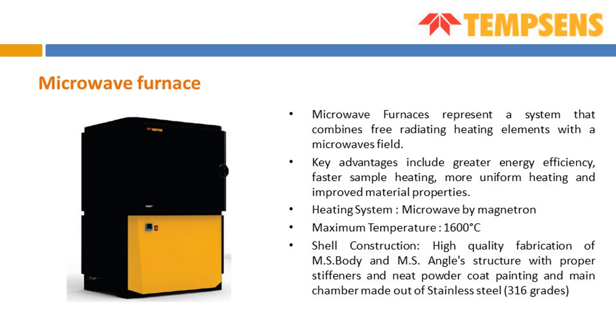Maximum temperature we can go up to is 1600 degree centigrade, and it uses a magnetron. We basically use magnetrons of different wattage, 900 watt, 1.2 kilowatt, up to 3 kilowatt. So based on the size and volume of your workpiece and the power needed, we design the number of magnetrons needed. Magnetrons are also of different types, like air-cooled magnetron or water-cooled magnetron. So we check what type of magnetron we are going to use, what cooling arrangement, or what type of controlling is there to control the magnetron efficiency.